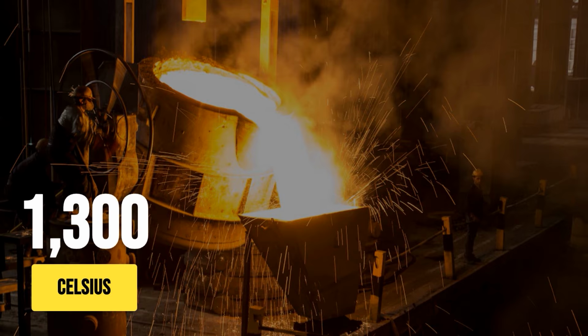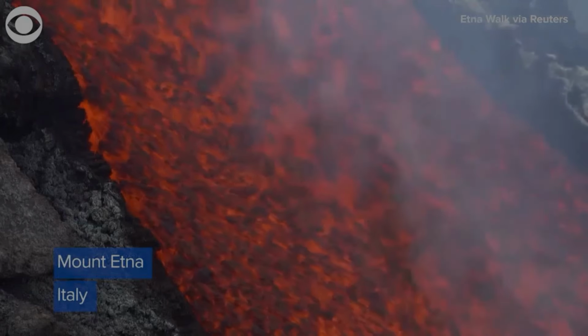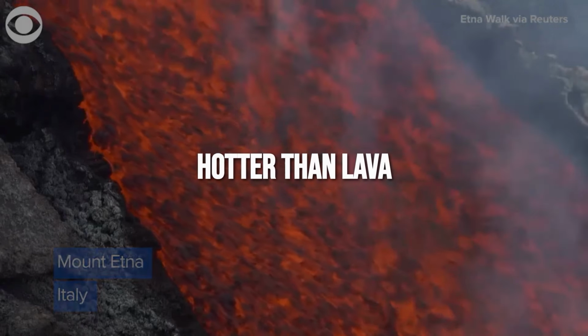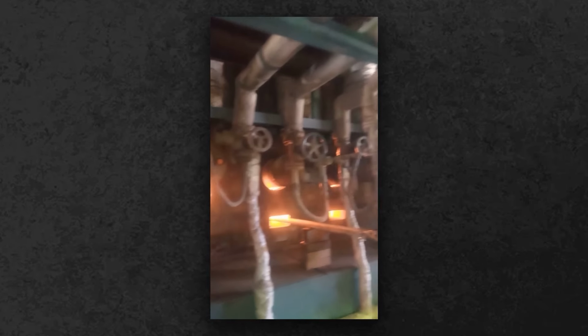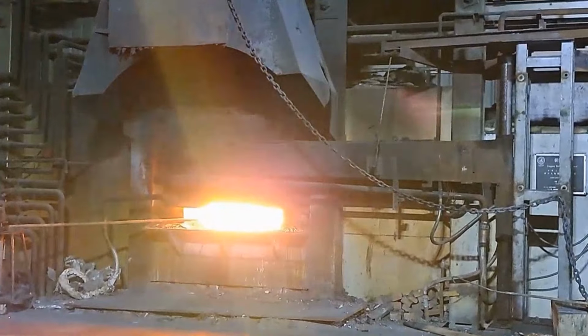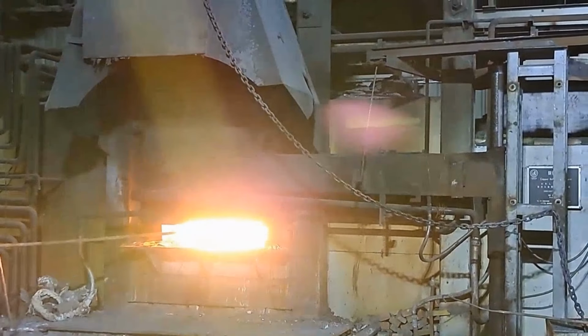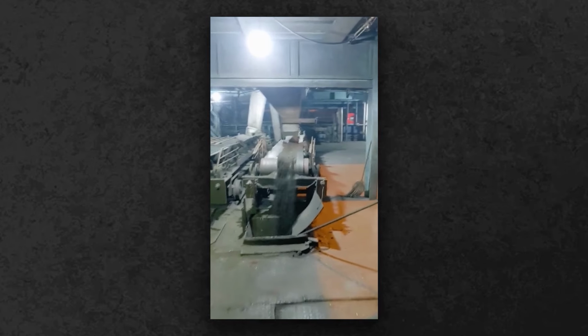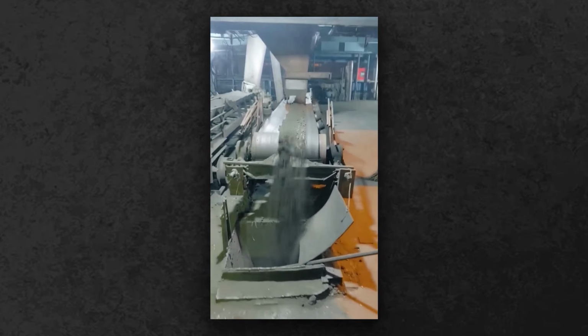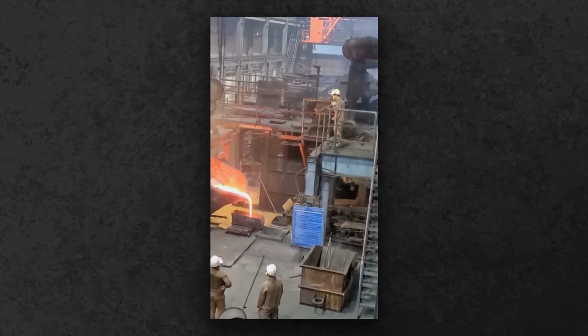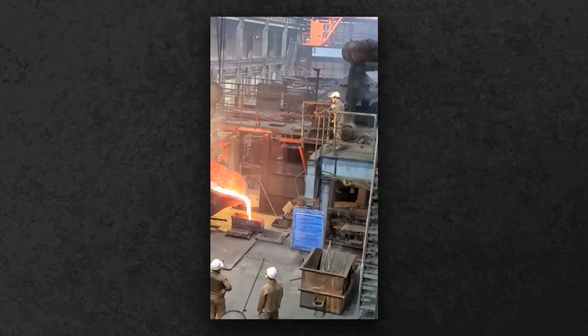Inside the smelter, copper concentrate meets temperatures as high as 1,300 degrees Celsius, hotter than volcanic lava. The process is almost self-fueling. As oxygen-enriched air blasts into the flash furnace, the concentrate ignites in a violent reaction, releasing enough heat to keep the fire raging without extra fuel. Silica sand, called flux, is added to bind with iron and other impurities. In seconds, the molten mass divides.